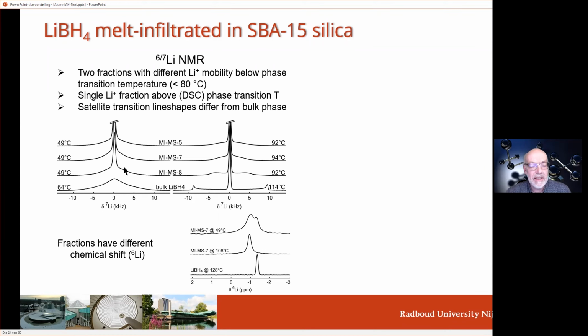And again, is this one lithium species or are there multiple? And for that, we resorted to 6 lithium. 6 lithium NMR only has a very small quadrupolar interaction. It's not noticeable in the spectra. And then we looked at the chemical shifts again, and that proved that in all these melt-infiltrated samples, actually we have two types of lithium as well.